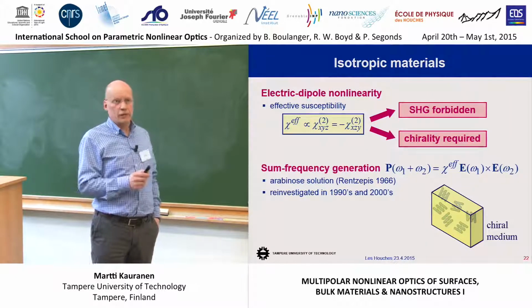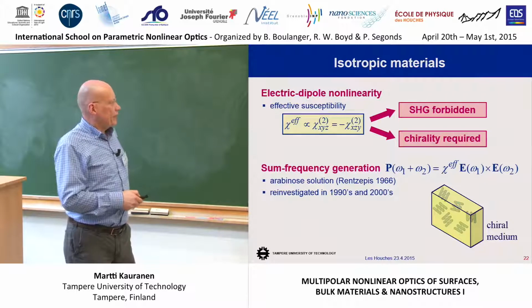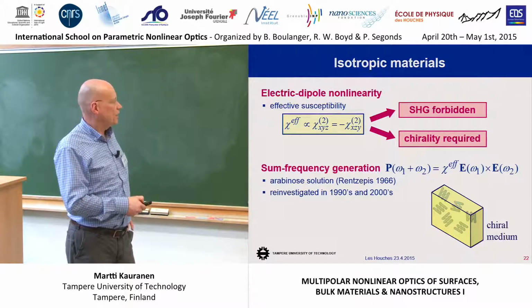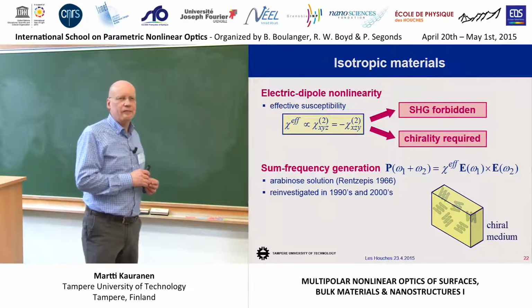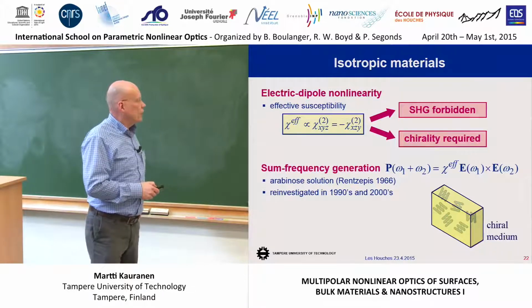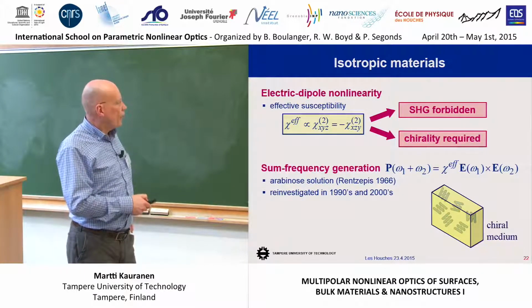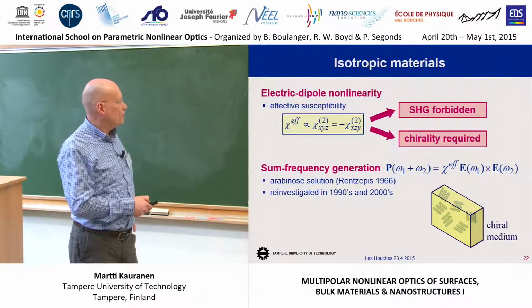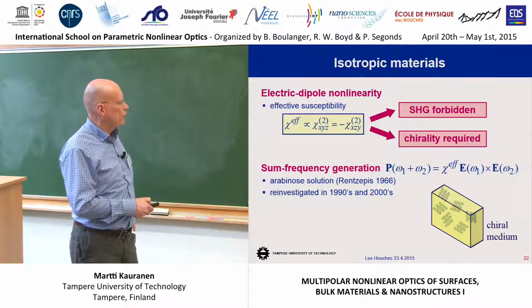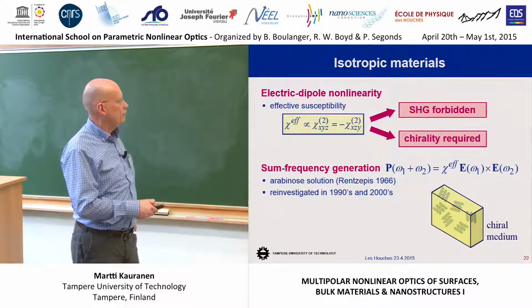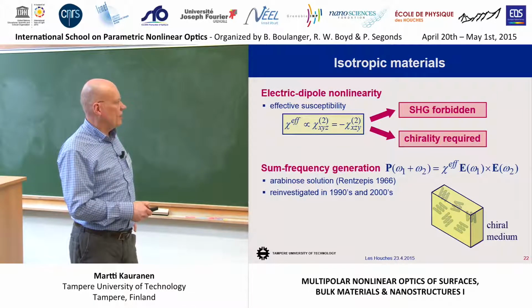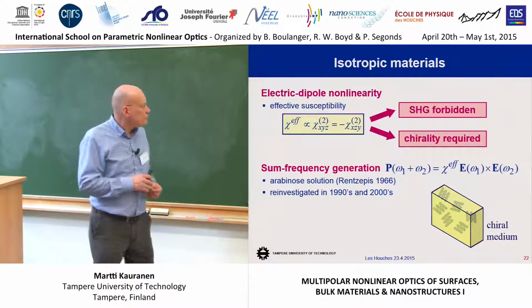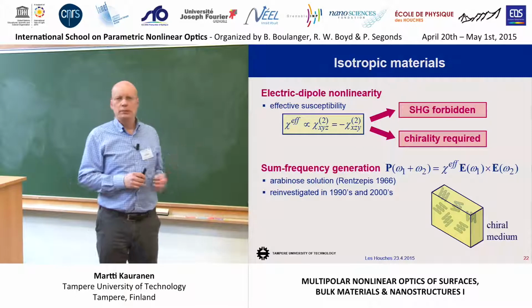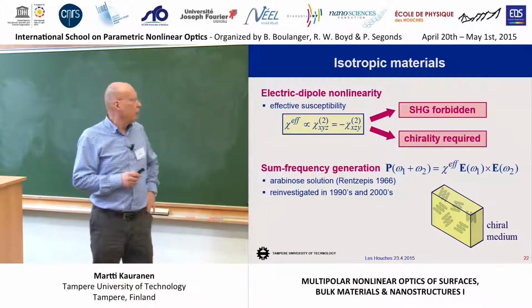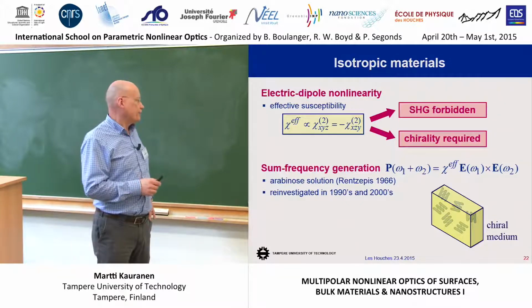And we can try to do some frequency generation. The first attempt for this one was already from 1966, almost 50 years ago. So really, let's say, very early days of nonlinear optics. And it turns out that when you put all of this together, you find out that the vectorial source polarization for sum frequency generation here depends on this effective susceptibility, and then you get a cross product between the vectorial fields at the two input frequencies. And this first experiment was done in an arabinose solution. Arabinose is a sugar, and sugars usually have handedness, and they did measure a response.